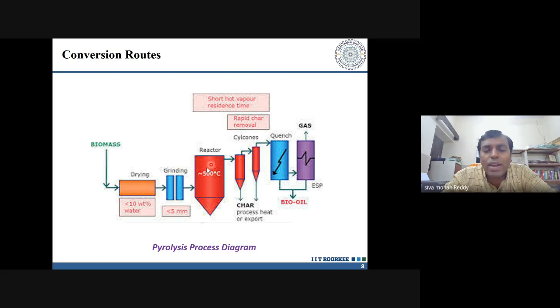Now once the biomass is fed to your pyrolysis reactor, we see that it gets degraded into three phases, that is solid, liquid, and gas phase. Now the gas phase usually comprises hydrogen, CO, methane, and carbon dioxide, but in different concentrations. From the top of the reactor, it goes to a cyclone separator, where you can separate the gas from the solid particulate matter. This hot product mixture is going to be quenched.